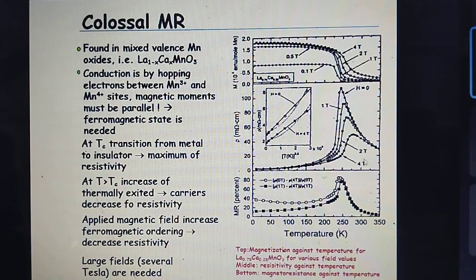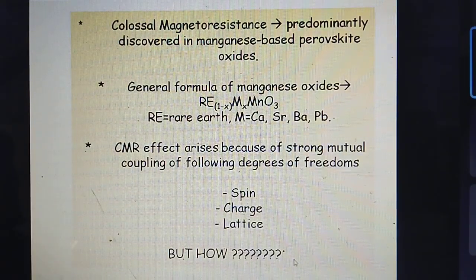So there is a tremendous change in the resistivity, a tremendous change in the magnetization, and a tremendous change in the magnetoresistance values, which you can see is about a percentage. At a temperature, the amount of change is about 40, 60 and 80% of its original value at the low temperature. So, colossal magnetoresistance is predominantly discovered in manganese-based materials, which again have a perovskite-based structure.